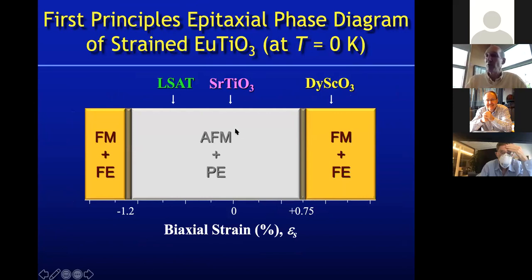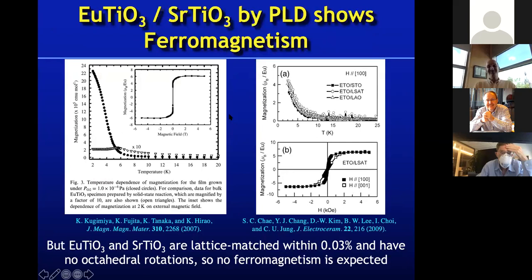And I mentioned that we were the fourth group, I think, to publish on europium titanate. I should point out that the first three groups saw that no matter what they put the europium titanate on, it was ferromagnetic. Okay, so let me show you that. To me this is a great control experiment. Here are the magnetic properties of bulk europium titanate, shown by these upside down triangles, the one that says ×10. So this is looking at bulk, and in bulk europium titanate is antiferromagnetic.